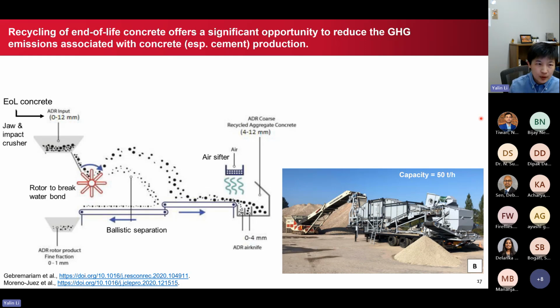So for example, in this process, they start with the end-of-life concrete, and first use a jaw crusher and impact crusher to crush the rubbles into smaller materials, and then have this rotor to essentially separate the crushed particles based on their sizes. And then here is an air sifter to further break it down into different sizes. So after this process, you will have 3 different parts here. The first one, the coarse part, is of the size 4 to 12 millimeters, and then the second part is the size less than 4 millimeters, and the finest part would be less than 1 millimeter.